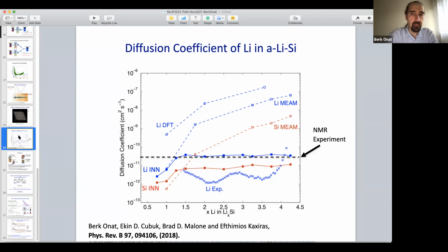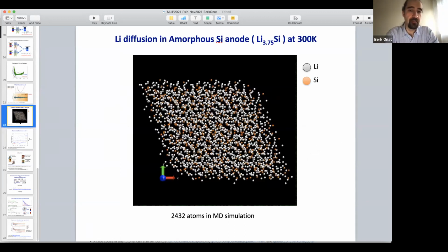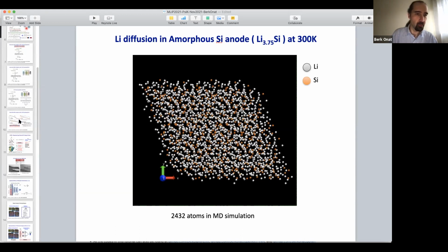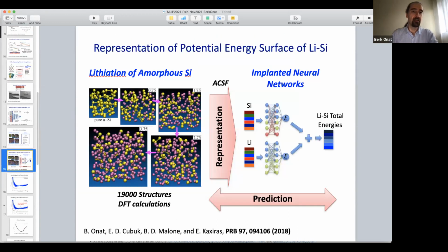We didn't check the finite size. I can answer that one immediately. We didn't reduce the structure that much. We always selected very large structures, a couple of thousand atoms, because we know the cutoff, and we need to extend that cutoff so we can capture amorphous structures better. For example, in small systems in DFT, you don't get a good amorphous structure. It just replicates itself because of the periodic images, since you have really small structures, like here, for example. Let me show one. Here, this pure amorphous silicon has 64 atoms inside it.